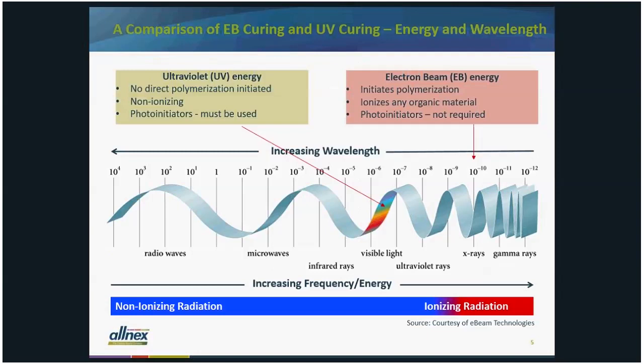And just another way of looking at the energy differences, you can see that the UV energy again is in the UV tending a little bit into the visible light, that energy is not strong enough to directly polymerize the oligomers and monomers that are used in energy curable coatings. So you have to use a photoinitiator. In contrast to that, the energy with electron beam curing is high enough to initiate polymerization all by itself. It ionizes organic materials, and so photoinitiators are not required.